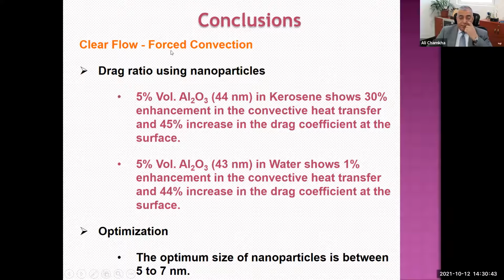For clear fluids of forced convection, the drag ratio using nanoparticles, which we calculated: 5% volume fraction of alumina, 44 nanometers in kerosene shows 30% enhancement in convective heat transfer and 45% increase in the drag coefficient at the surface. 5% volume fraction of alumina, 43 nanometer size nanoparticles in water shows 1% enhancement compared to 30. These sizes are very close to each other, but different. Kerosene or water, you have 1% here and 30% there. Enhancement in the convective heat transfer and 44% increase in the drag coefficient at the surface.